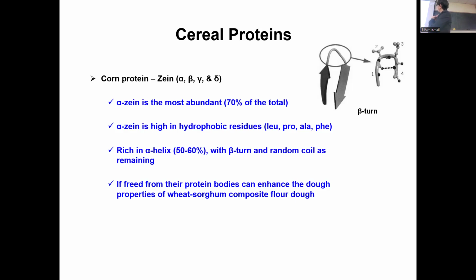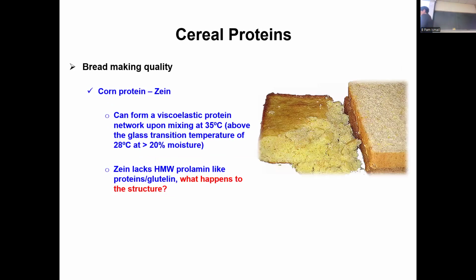That's what I want to remember here. When we try to form the dough, we have to mix above the glass transition, which is higher for zein compared to gluten proteins. So you can form a viscoelastic protein network at a higher temperature than room temperature, above the glass transition, and you need a higher moisture content. However, when we bake, the beta sheet formation is not stable. It gets destabilized and you get crumbling. So you lose that elasticity that holds the air during baking.